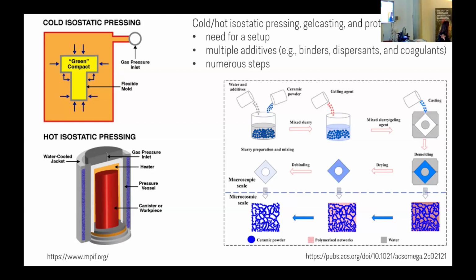So the novelty of this research is the preparation of the green body, and what we can do with these malleable, self-standing doughs as opposed to what people are doing in the preparation of other types of green bodies. So let's see what people do. There are isostatic pressing techniques. You use elastic molds and put a slurry of the ceramic into that mold, and then you isostatically pressurize the system so that you get a compact in the end. That is one way. You can also have pellets by compacting particles into each other through a powder compaction machine.